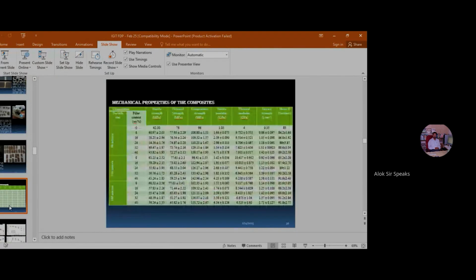So here is a chart which is giving you the different property values for marble dust filled polyester composite. In this particular work, my group has taken the same marble dust but of three different size ranges: 58 micron, 110 micron, and 155 micron. That's the average particle size. It is done with a purpose to find out whether the particle size has an impact on the properties or not. And we found that it has. If the particle size is less, then the strength is also less. If the particle size is more, the strength is more. There are specific reasons for that, which need special kind of investigation.